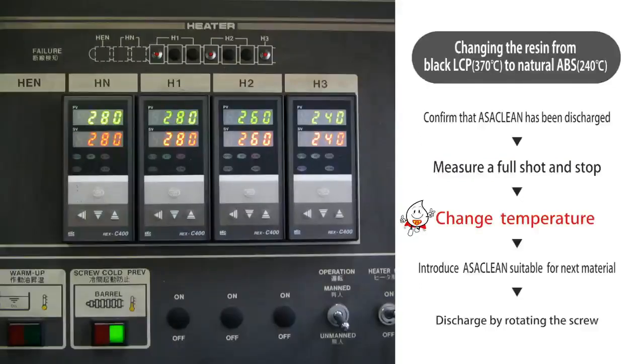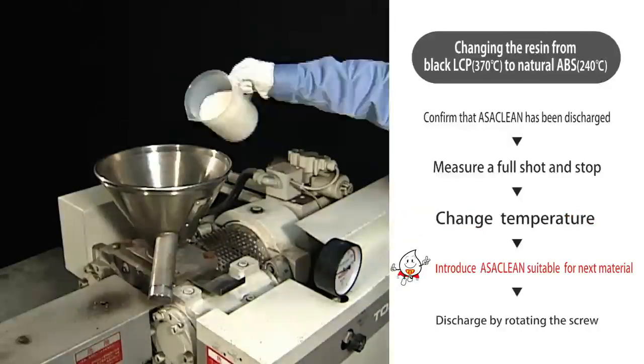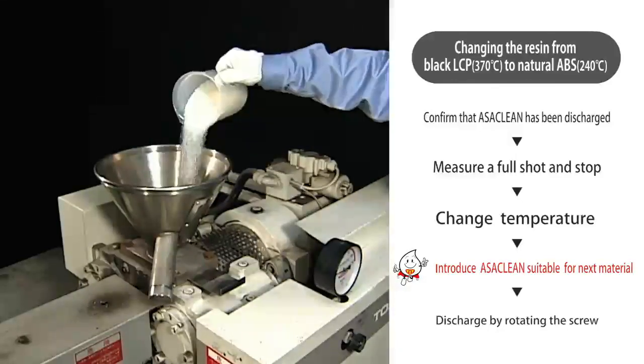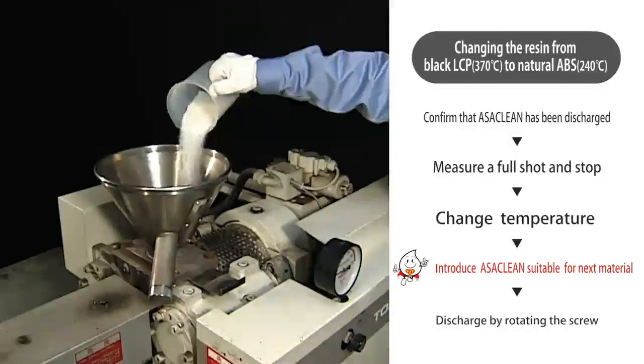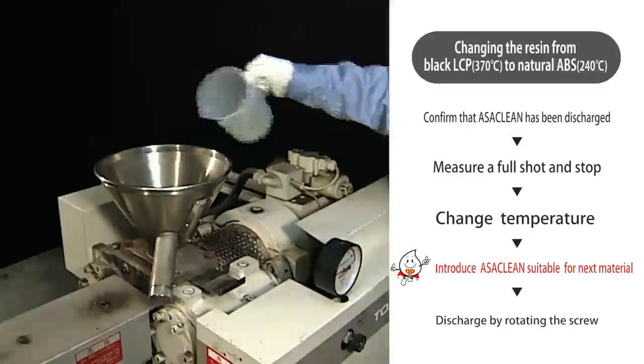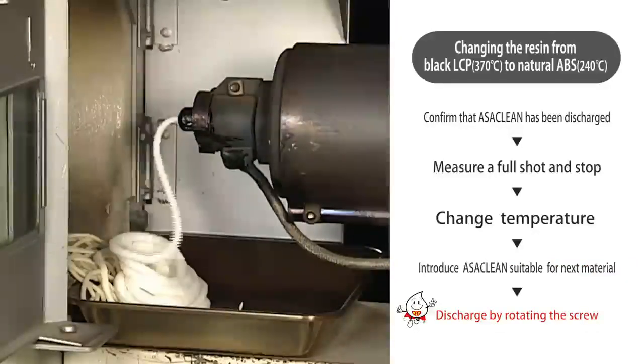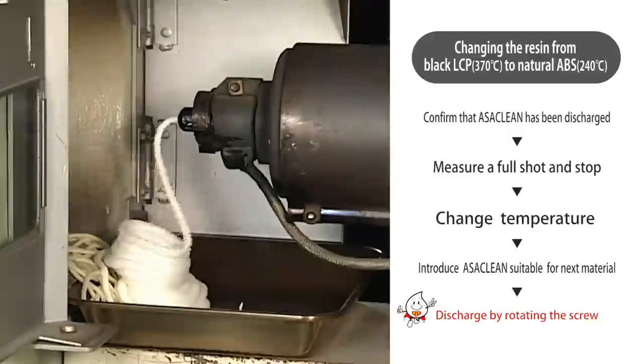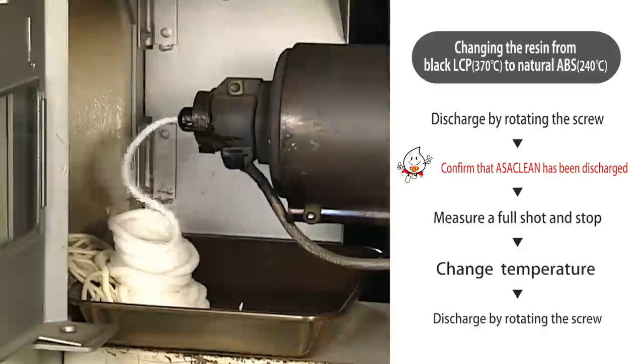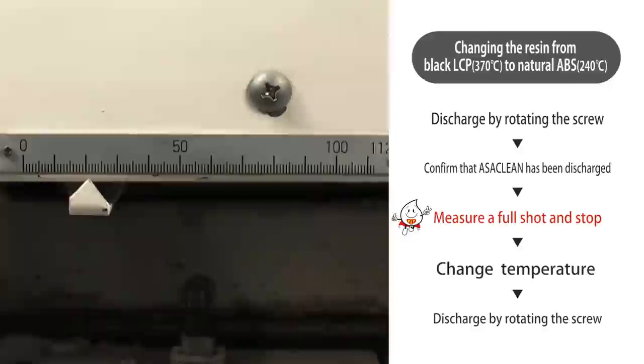Perform the first temperature change. Change the setting near to the lower temperature limit of the ASACLEAN being used. In this example, the temperature is set to 280 degrees. Confirm that the set temperature has been reached and then introduce a grade of ASACLEAN that is suitable for the next material. Perform an air shot using a full shot size, then discharge ASACLEAN by rotating the screw. Finally, stop screw rotation when a full shot has been plasticized.